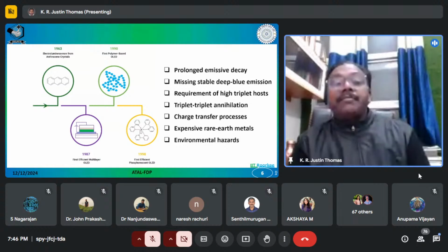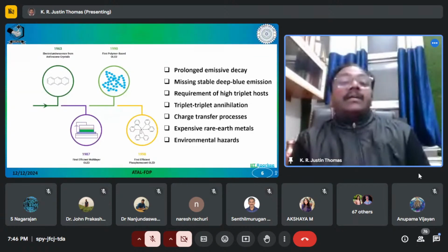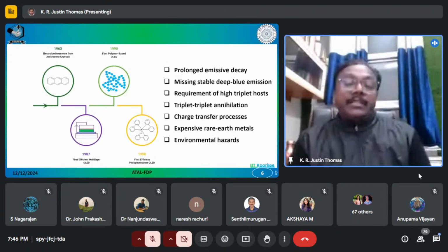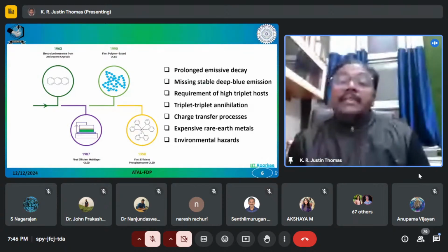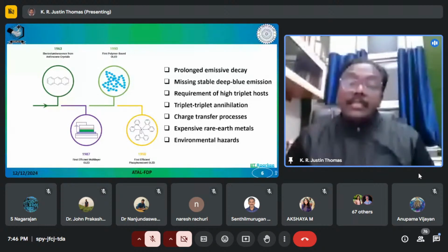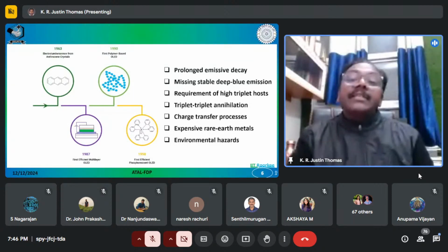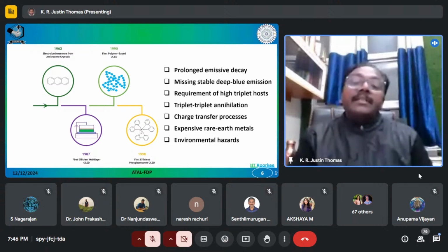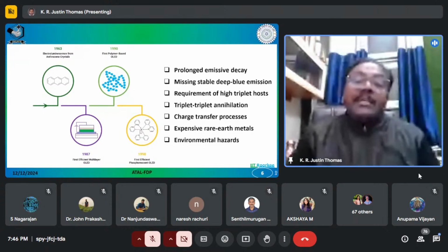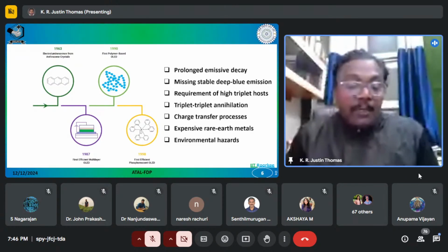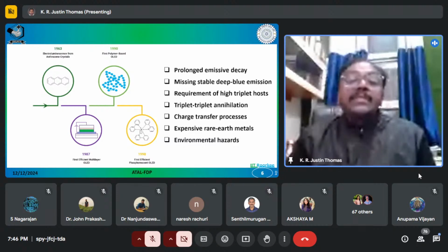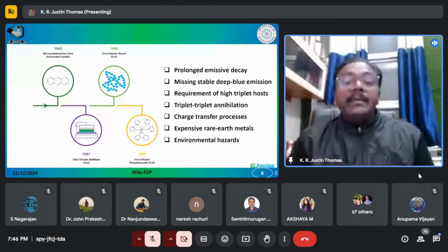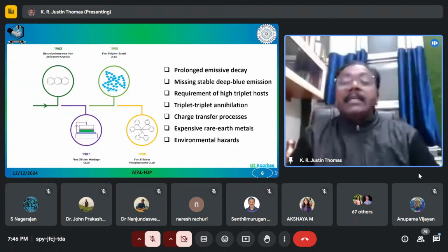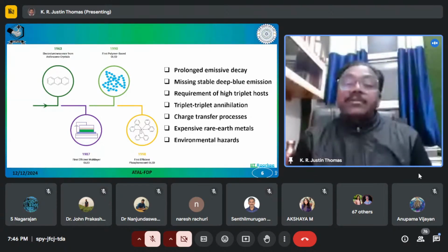So even though internal efficiency can reach 100%, because of the low quantum efficiency, you are reducing the efficiency of the device. The internal quantum efficiency of 100% can be realized only when the fluorescence efficiency is also 100%. But the fluorescence intensity is decreasing, and that is what is happening in most of the metal complexes. You might know that in ruthenium and osmium complexes, it is less than 1%. In iridium, it is not that low; however, you can have around 10% to 20%. So you are still having a challenge with these complexes.